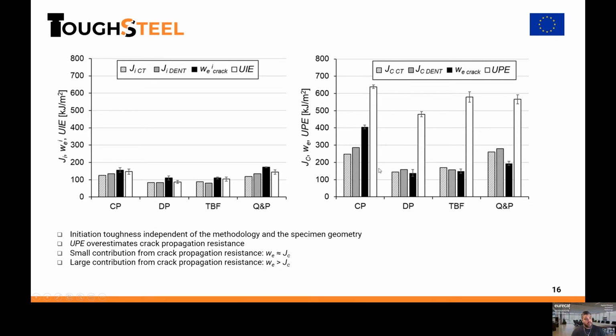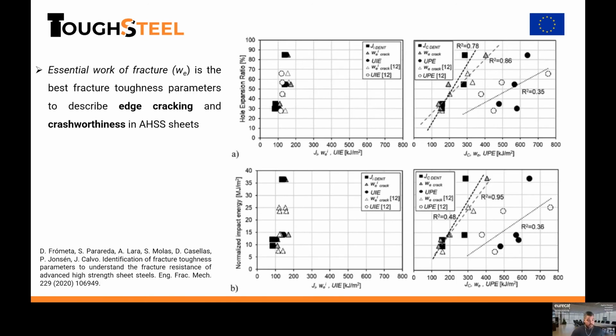Well, here it is larger. But what happens in materials with a really large contribution from the propagation resistance, like the complex phase? Here we can see that the essential work of fracture, as we said at the beginning, represents the energy for the full fracture. In this case, JC is only the initiation, more or less, for a small crack advance. The essential work of fracture better represents the full crack propagation resistance of the material. In summary, when trying to correlate the fracture behavior of these high-strength metal sheets, talking about edge cracking or crack formation in a crash, we have seen that the essential work of fracture is the most suitable parameter to describe the overall fracture performance, or fracture resistance, of the material.